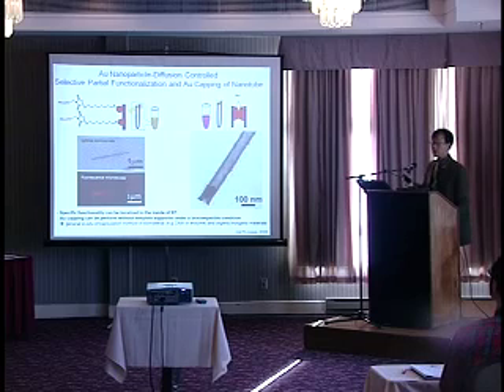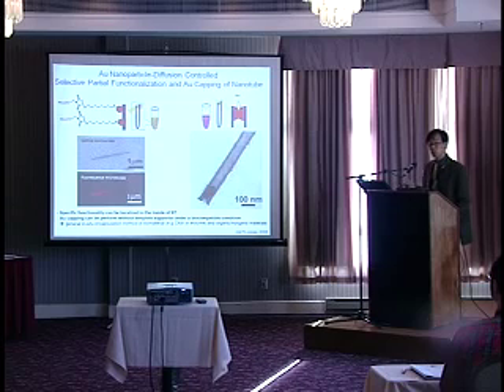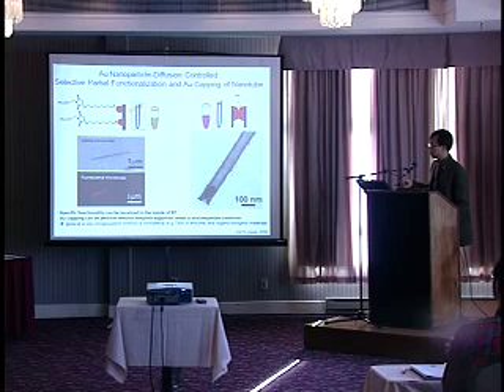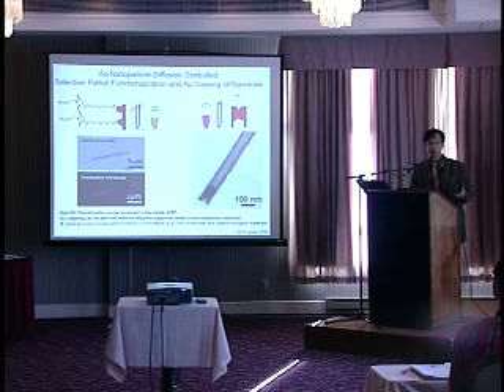So what we were trying to do was control the diffusion of gold nanoparticles into the nanotube, so we could perfectly control the gold nanoparticle diffusion only at the entrance of the nanotube, and then use those gold nanoparticles as a seed to grow more gold to clog the pores of the nanotube. This TEM image shows that the gold is completely blocking the entrance of the nanotubes. And using the same technique, we also could modify only half of the inner surface of the nanotube with different chemicals. This is another technique to introduce one or two or multiple chemicals onto the inner surfaces.